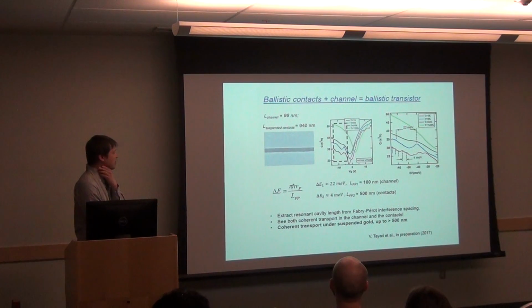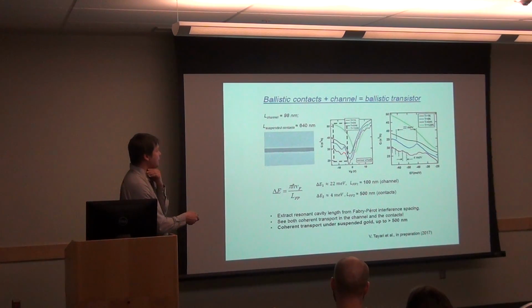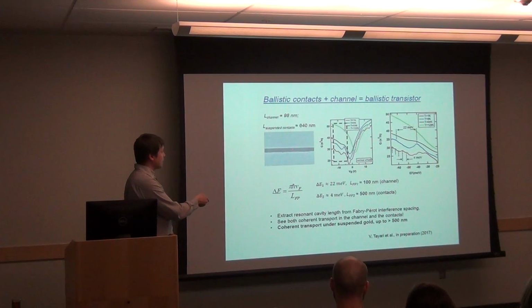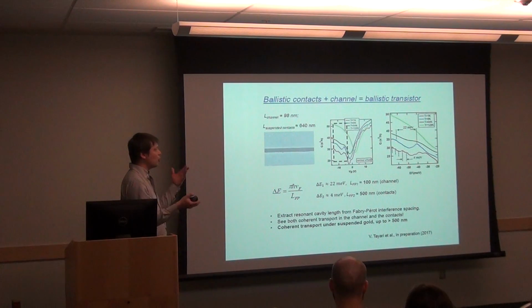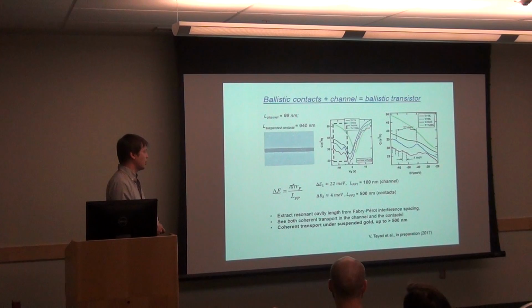So we can make these ballistic devices, and by measuring the spacing between interference fringes, you can actually get the length of these cavities. For instance, these small fringes here, 4 milli-electron volts, correspond to the suspended length here, the 500 nanometer length. And for the 100 nanometer channel, you can see it as well in a 22 milli-electron volt spacing. And if you raise the temperature, then these resonances go away because you're scrambling the quantum phase. It's not coherent anymore.